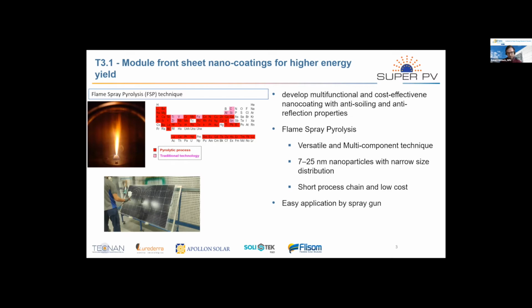After the production of the nanoparticles, they have to be dispersed in a liquid formulation. Here, Loredera and Tecnan decided to go for a formulation which is feasible for the spray gun that you can see here in this image. So this makes it very simple to apply these nano coatings to the PV module in the manufacturing process, either by the spray gun, or you can also apply it maybe in the field, for instance, when you have modules which have no coating on the front side, or in case nanoparticles are degrading somehow over the years in the field and you want to renew your coating, you can simply apply it also with a spray gun in the field. So this is a very easy application with this spray gun method.